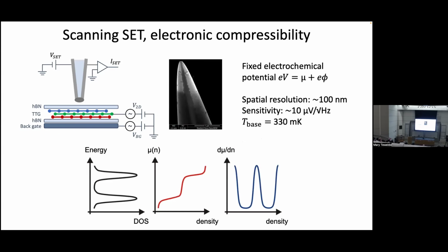So the way we do this in experiment in real samples is like this. We have a quartz rod, we evaporate aluminum, we oxidize it to form the tunnel junctions, we do one more aluminum evaporation right at the apex here. That gives you about a 100 nanometer or 50 nanometer, somewhere in that range, island at the very tip of this quartz rod, which we can then put next to some sample which we'd like to study to learn about its electronic properties.